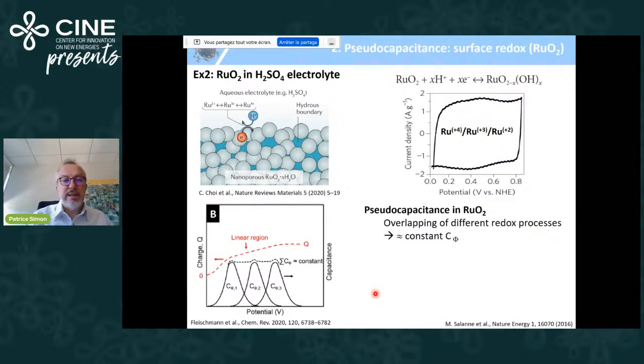And then another example is ruthenium oxide in sulfuric acid electrolyte. You can see that more or less you have a very nice rectangular CV with redox bumps here. This CV is redox. This CV is not capacitive in the sense that it is not double layer. It's a redox process where the ruthenium oxidation state changes with proton intercalation. And what you see, in fact, is that this pseudocapacitance is explained by the overlapping of different redox processes, ruthenium 4, 3, 2.